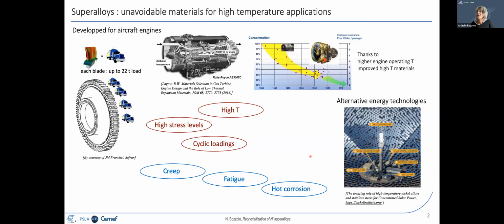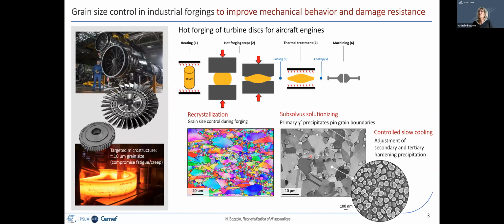Now we need to make pieces with these materials, which have extraordinary properties. I will go back to the turbine disc application. For making a turbine disc, the material undergoes a number of thermomechanical processes: heating, hot forging, or deformation in general, and subsequent heat treatments. During all these steps, the material undergoes a number of metallurgical transformations and microstructure evolutions, and recrystallization phenomena are those by which the grain size can be controlled. In these materials you can find second phase particles, the large precipitates you can see here, which are used for controlling the grain size by the Smith-Zener pinning phenomenon.